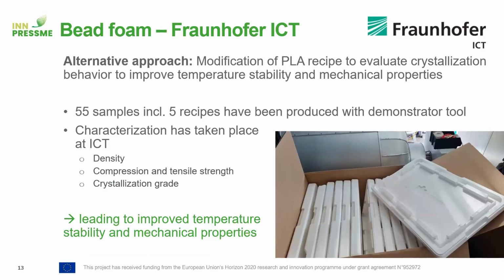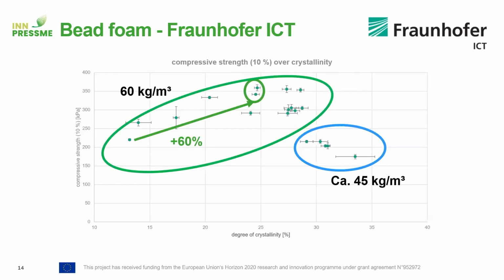And this was also, I would say, the right approach in the end, as after quite a lot of tests and characterization, we could improve the properties of the PLA bead foam with regards to the fusion of the beads, mechanical properties, and temperature stability. This is just a quick chart showing that the compression strengths could be improved at the same density of foam just by modification of crystallinity of the foam by 60%, which is quite a nice result.